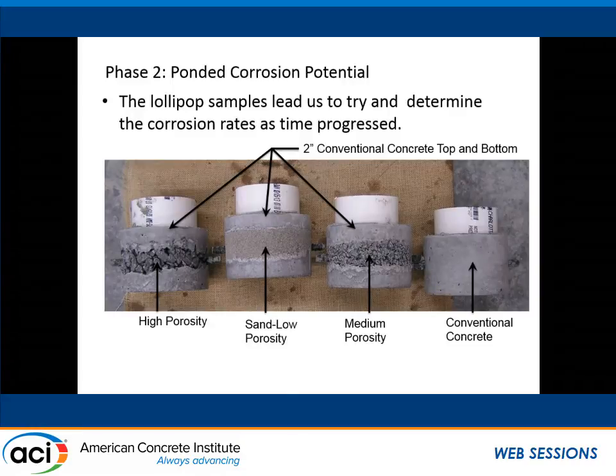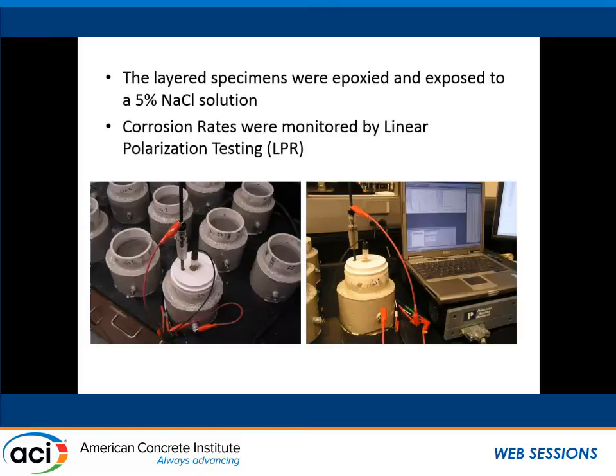We're actually doing some ponded corrosion potential testing, long-term testing right now, where we've got a conventional layer of concrete, a layer of pervious with some steel in it, and then a conventional, so it's kind of 2-inch, 2-inch, 2-inch there. We've got a PVC pipe in the top, and then we use that to pond a chloride solution, and then we can measure the corrosion potential of what's happening. We did a very high porosity coarse pervious, a medium porosity 3/8 pervious, and then a lower porosity, sand-only pervious concrete, and then a control. We have rebar running through the middle of all those samples.